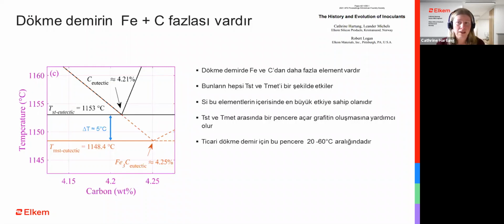And all of them affect the stable and the metastable line. So they can either push these lines together or they can open them up. One of the most important elements, which we know we have a lot of in cast iron, is silicon. Now, silicon is really nice because it opens up this window. So instead of having this 5-degree difference, depending on the silicon level, it is from 20 to 60 degrees. So that gives the iron more time to get the nucleation started and to complete the solidification in time. So that's the recap. Next.